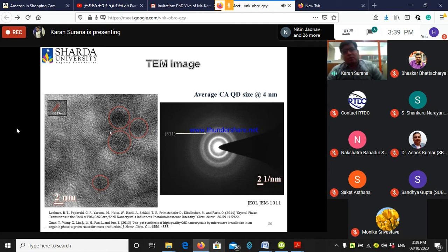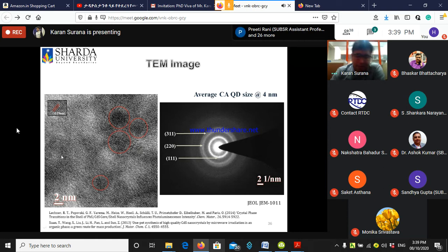The core shell quantum dots. There was a substantial time between the synthesis and when we were able to carry out the TEM characterization. Because of this, individual particles cannot be spotted because of the Ostwald ripening which happens in the quantum dots, and so they've all merged and clumped together. Although if we look carefully by enlarging this image, we can see that a dark center is there with a very light exterior shell.